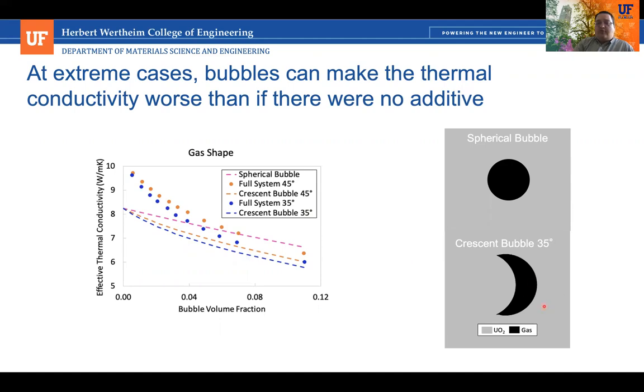And the reason for that is because we've changed the shape of the bubble. In the case where we're assuming there's no additive, we get a spherical bubble. And when we have additive, we get this crescent bubble where we've spread the gas out a lot more in the direction perpendicular to heat transport. And so it's blocking much more of the composite particle, the high thermal conductivity particle. And essentially it's approaching the line that I'm showing here. The blue line or the orange line are the thermal conductivity if we just had a bubble with no particle at all. And so they started approaching that, which of course is going to be worse than the spherical bubble.